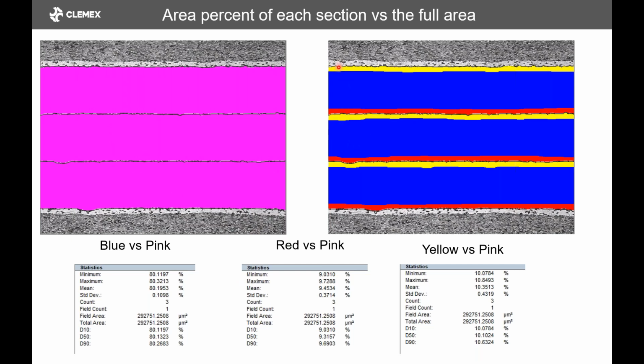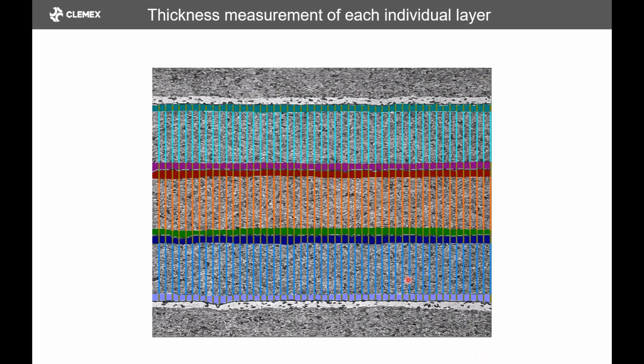Then we can measure the top and the bottom layer for each of the pink. So we have a value here. So we have 3 counts. And then we have a distribution in percentage, area percent in this case, of each layer versus the whole strip. Then we can also do the thickness measurement of all the layers. So we can see that all the layers are measured individually, and so we have the result that we need. This is what was required at the time for this customer.